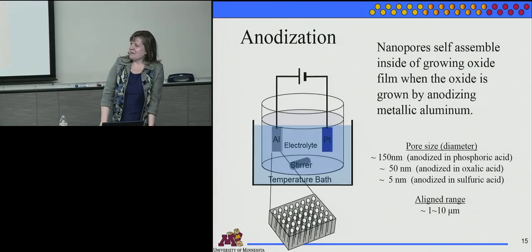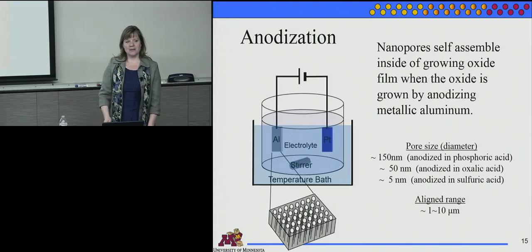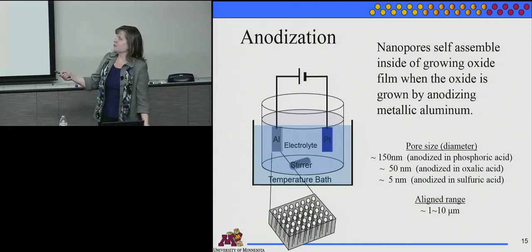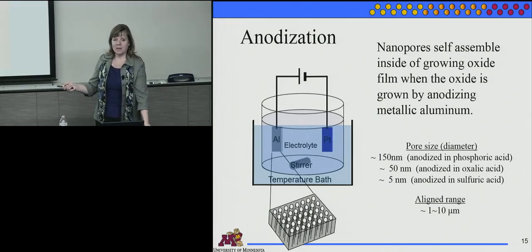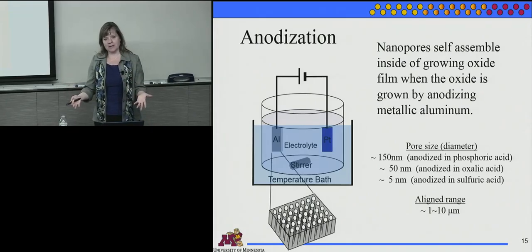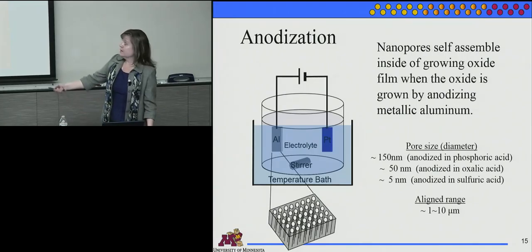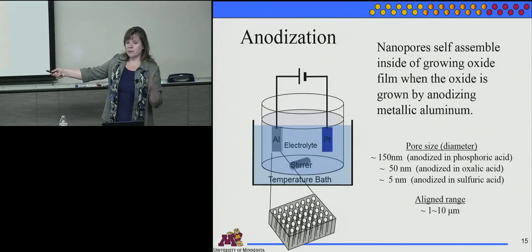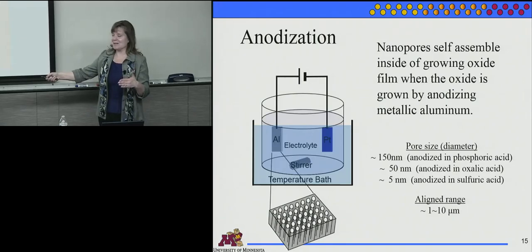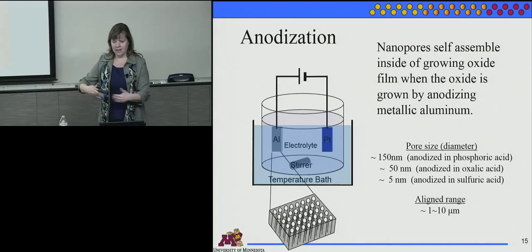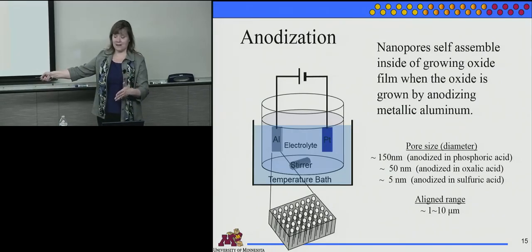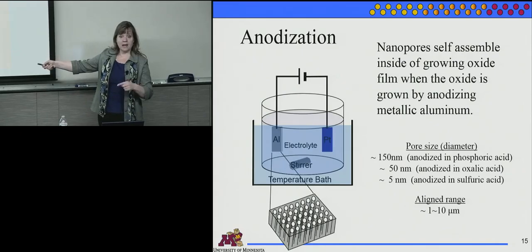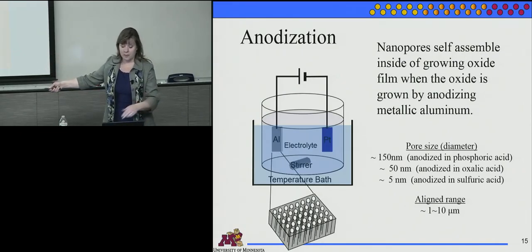All right, well, why anodic aluminum oxide? So just in case you haven't heard before, what we're going to do is take aluminum and make it the anode of an electrochemical cell. So whenever you hear anodic aluminum oxide, it's because it's an anode when you make it. So you start with aluminum, but just remember, because even after saying this sometimes, I have people say, why would you be able to electroplate when you've got a matrix of aluminum with holes in it? But this is not aluminum, it's an oxide. So we start with aluminum, and as the oxide grows, it has nanopores in it.